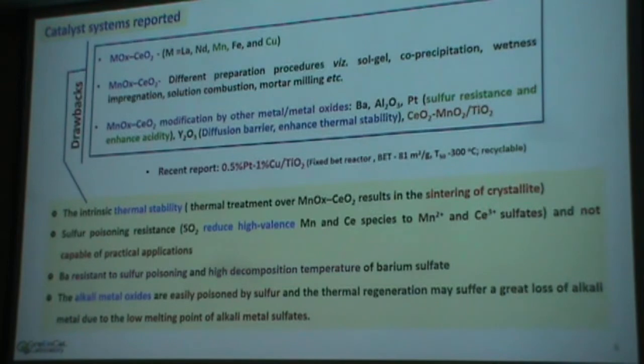But this combination has a drawback: although it is highly efficient, thermal stability is the main issue with the Mn-cerium combination because it easily gets sintered at high temperature, so it cannot be applied practically. Several researchers have added alkali metals to it, but alkali metals are still sensitive to sulfur poisoning, and barium was found to be resistant, but its decomposition or regeneration is quite difficult. And with the other alkali metal, mainly potassium, there is a great weight loss during the regeneration.